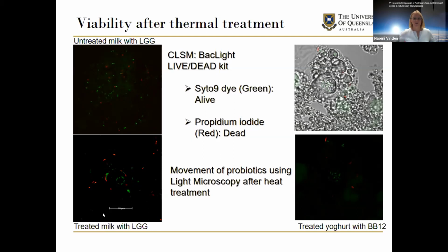So, to determine viability, I use confocal laser scanning microscopy using the BacLight Live/Dead kit. This has 2 fluorescent dyes: SYTO 9, which is the green. So you can see in these images here, you see little green bacteria, and that means they are alive. And propidium iodide, which fluoresces red, and that binds to them when they are dead. So red is dead, green is alive.